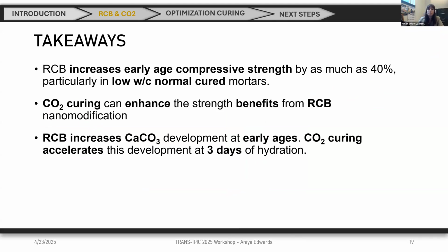So some takeaways here on this first part: yes, recovered carbon black increases the early strength of materials. I didn't show all the data, but particularly when we have low water to cement ratio, we have greater results. And then another important thing is that CO2 curing can enhance the benefits of using recovered carbon black. So we are adding additional strength, so therefore we can leverage the use of the two of them together, especially for lower amounts of carbon black.